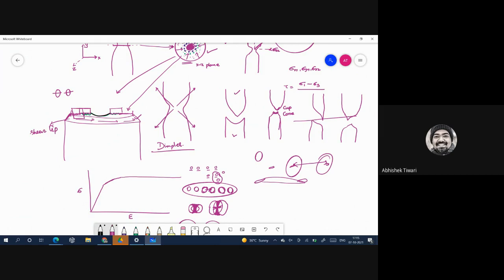You will see in the lecture, which I will upload, that in brittle fracture, you will not see signatures like dimples. You will see tongues, and you will see cleavage. In cleavage fracture, you will see river patterns. Those are the signatures of cleavage fracture, or brittle fracture. But those cannot be related to the fracture toughness. And that's the major difference between the fractographic information which you get from the ductile material in comparison to what you get from the brittle material. So ductile material can be related to the material property, which is fracture toughness. But cleavage fracture or brittle fracture surface cannot be, so far it has not been related. I should say that, because there could be a relation which people have not found so far.